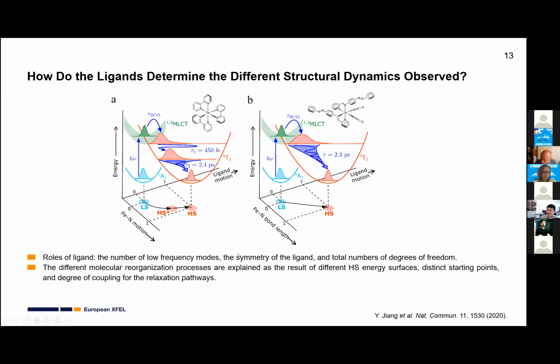By this comparison, we show the role of the ligand: the total number of low frequency modes, the symmetry of the ligand, and the number of degrees of freedom. And the difference between these two molecules is the result of the different high spin energy surfaces, different starting points, and the degree of coupling for the relaxation path.